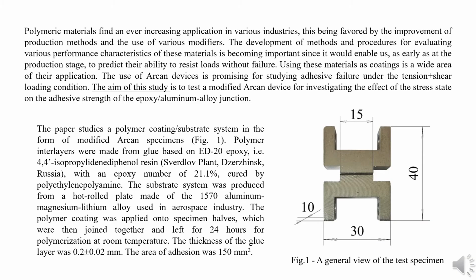The paper studies a polymer coating substrate system in the form of modified arcing specimens. Polymer interlayers were made from glue based on ED-20 epoxy. The substrate system was produced from a hot-rolled plate made of the aluminum-magnesium-lithium alloy used in the aerospace industry. The polymer coating was applied onto specimen halves, which were then joined together and left for 24 hours for polymerization at room temperature.